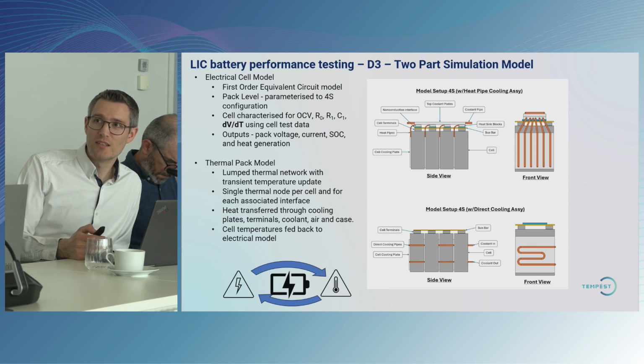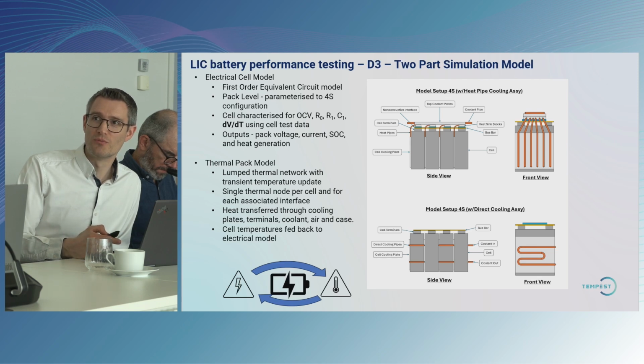As well as the Thevenin parameters, I just again highlighted, in bold you see there the dV by dt term, the entropy term, and we've used that term to really explore how that affects the heat release rate, the reversible part of the heat release, as the chemical reactions during the charge and discharge release and also absorb heat during the charge-discharge cycles.